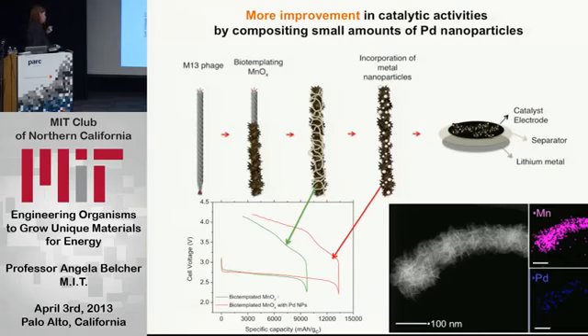And so we started thinking, or I should say, she started thinking about what we could do to improve this. And so we were able to take our virus and grow this biotemplated manganese oxide material. It's a mixed valent manganese material, and then we wrapped it with a little bit of polymer, and this polymer had the ability to nucleate either palladium or gold nanoparticles to try to increase the catalytic efficiency of this. And so it actually makes this beautiful structure. I hope that you can see it here. This is the tip of a virus here, so it's a 100 nanometer length scale, so it's just part of the virus. But it makes these kind of spiky structures that increase the surface area of the individual wires, and the wires, when you put them together into this three-dimensional structure, increase the surface area even more. And this is the manganese, and then she's putting a little bit of palladium here, 1 to 3% is what she was looking at.